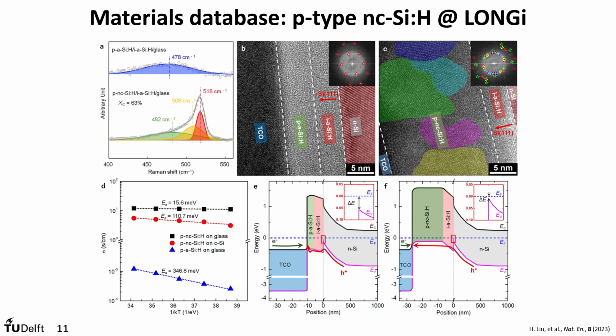And you see that also at the industrial level, all our postulations came true. Very low activation energy, very high crystalline diffraction, and essentially band-to-band tunneling happening in order to have the best possible efficiency. Here, we are talking about a fill factor that is in the range of 87%, which is unheard of when it comes to crystalline silicon solar cells until a couple of years ago. We thought that only gallium arsenide could get that type of fill factor.